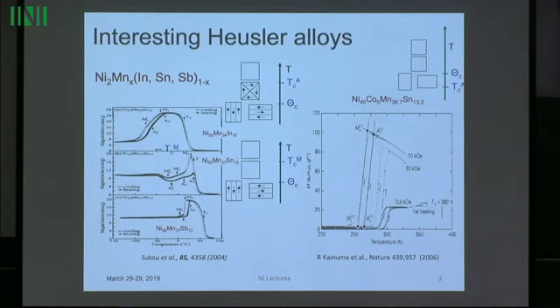It has no ferromagnetism. The austenite is not ferromagnetic, and the martensite is not ferromagnetic. But here's a quite interesting measurement with a very strong field. This is 7 Tesla. That's a huge field. You need an enormous magnet to make a field like that. It's the kind of field you get inside an MRI. Then you suddenly see that it develops a phase transformation to a very strongly magnetic state. However, if you do tests without that magnetic field, you won't see any magnetism. So that's the correct diagram.